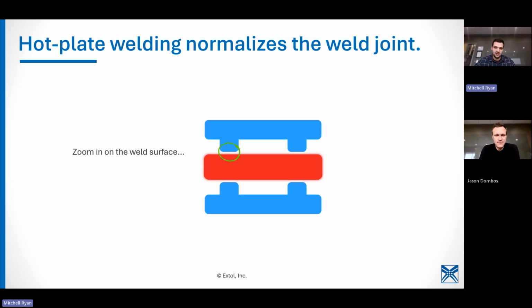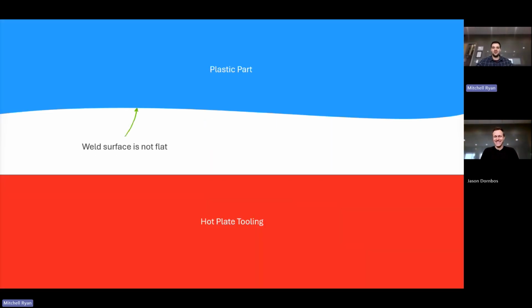So let's zoom in to the plastic part weld profile. And this kind of simulates, I guess, probably the other image of the part where you've got some high and low spots here. If you were to join this part together, bring it to a molten state and join as is, you've got a lower component on the right side of the screen here that would absorb all of the force or a majority of the force, and you'd get minimal force on this part, which could create leak paths.